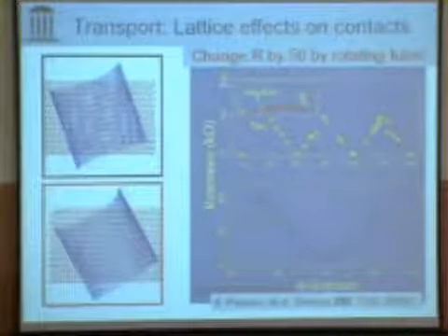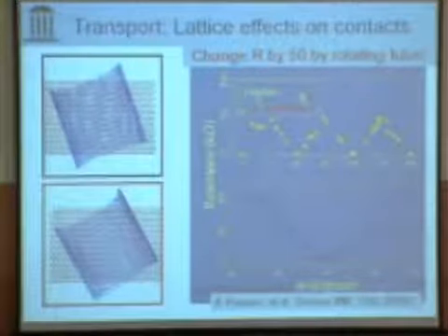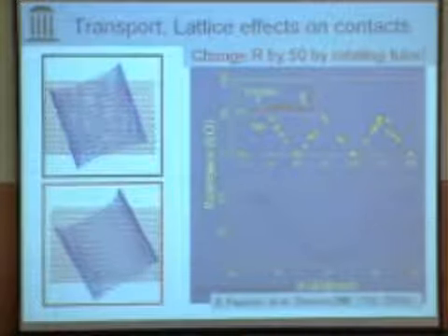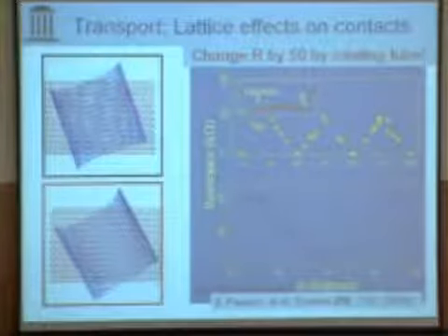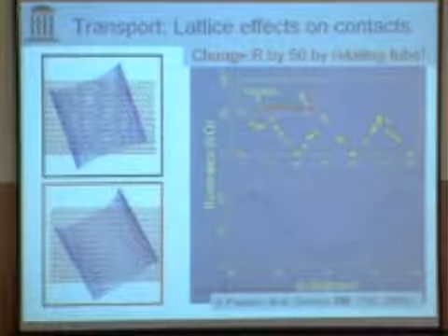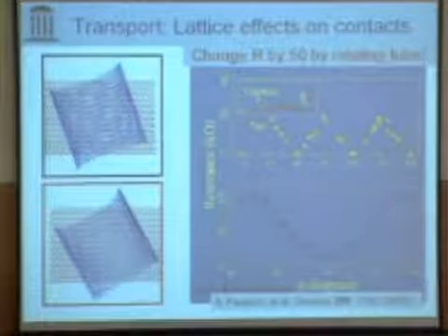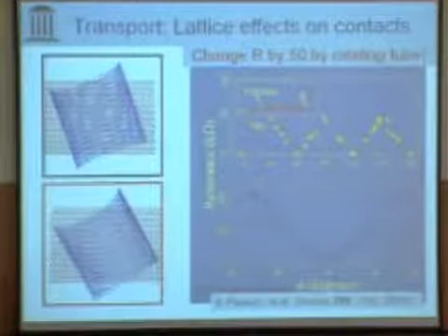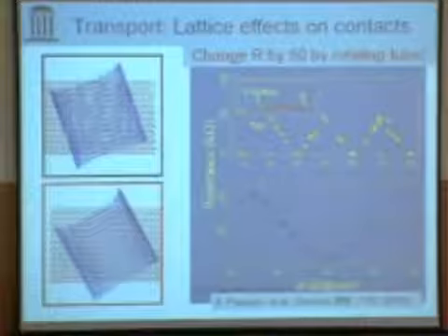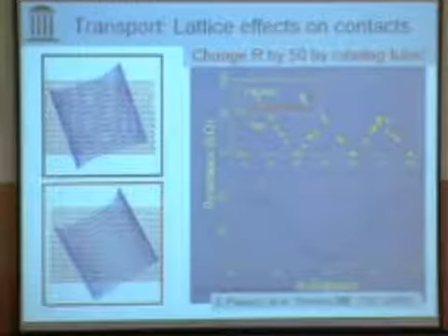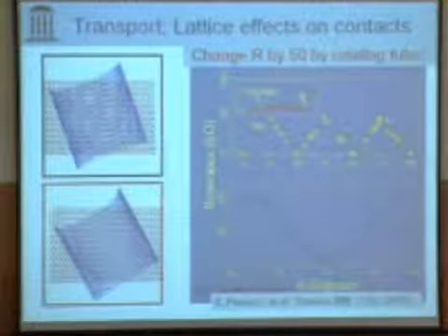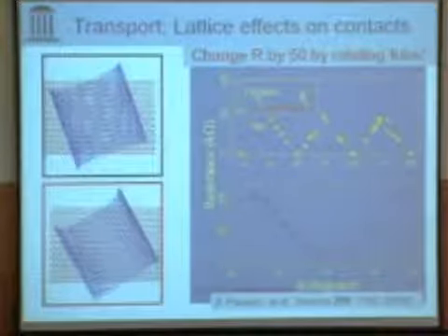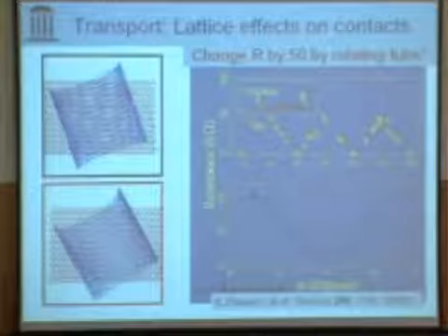We know these points here are where the lattices interlock because we measure the friction. We measure the point where the rolling happens. And so that allows us to pin exactly what we mean by 0 degrees here. That's when the lattices interlock according to rolling. And if you blow up the scale here, right here, you could see this phenomena here, where the resistance is high when the lattices are out of registry, but when they're in registry like this, the resistance is low.